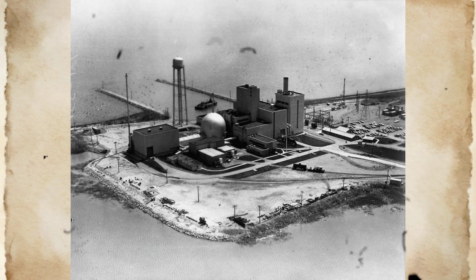When fuel temperatures reached critical levels approaching the melting point of metallic uranium, the fuel began to form liquid phases that had significantly different thermal and mechanical properties than the original solid fuel. The molten uranium could not maintain its original geometric configuration within the fuel pins, and it began to redistribute according to gravitational and thermal forces within the fuel pin structure. This fuel relocation changed the spatial distribution of heat generation within the fuel assemblies and created localized hotspots where heat generation exceeded the capacity of the already reduced coolant flow.